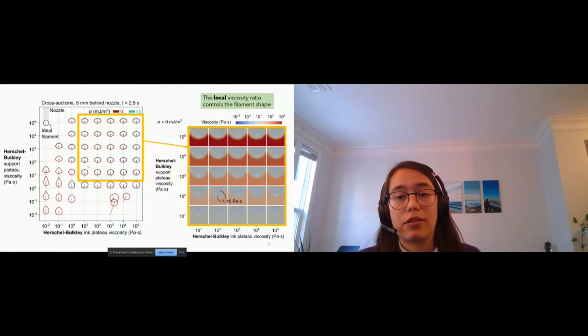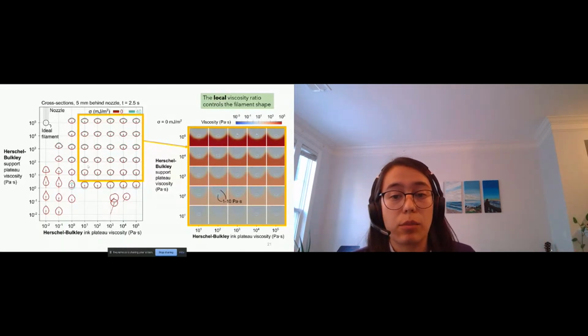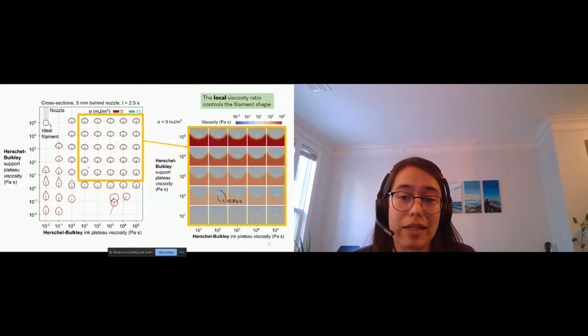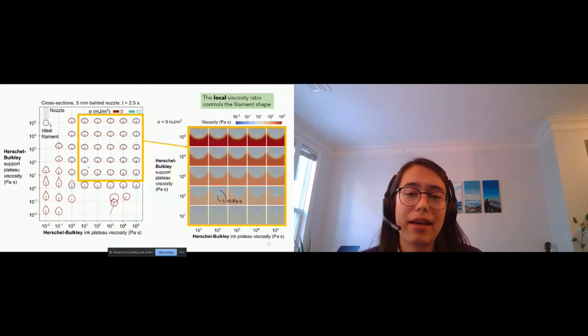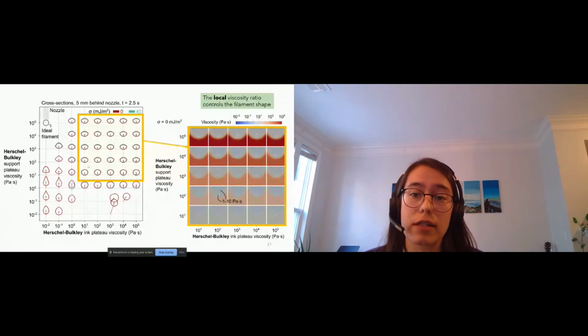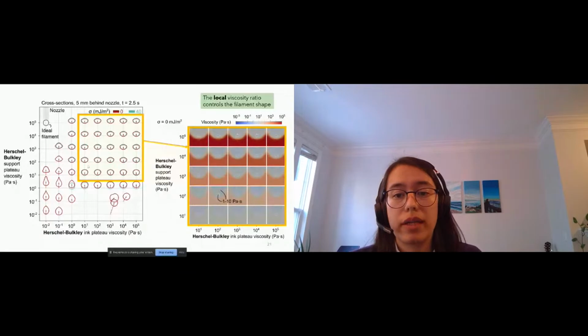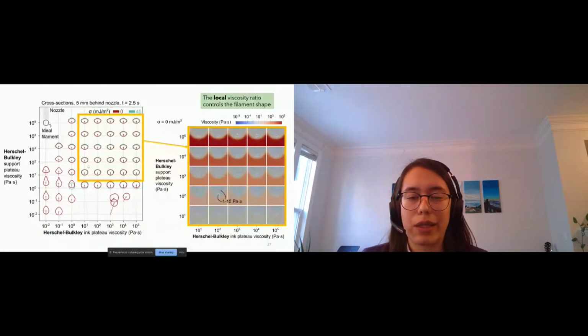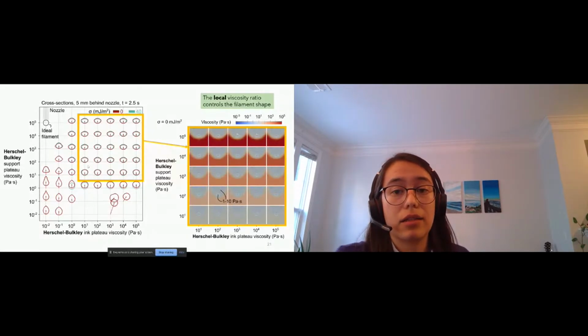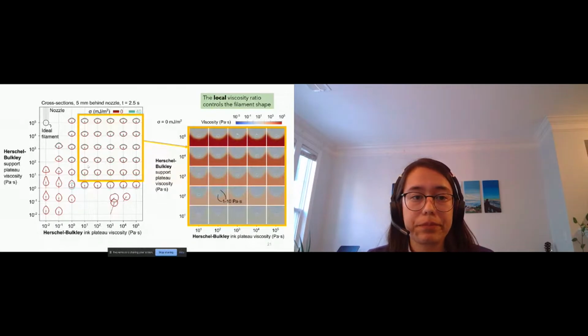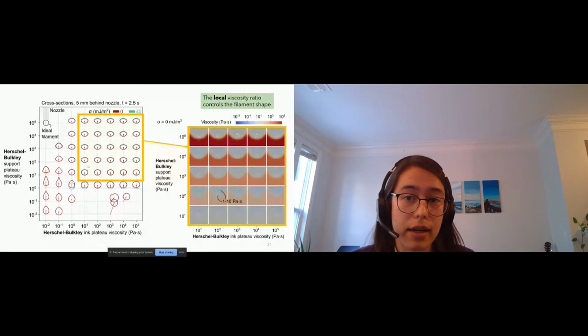And then there's a yielded zone outside of the filament where the support is at about 1 to 10 Pascal seconds. And then outside of that yielded zone, all of these supports are at a different viscosity, which is their plateau viscosity. So because we have the same viscosities within the yielded zone locally, that means we have the same local viscosity ratio for all of these plots, and that's why we get the same filament shape. So we learned here that the local viscosity ratio is what controls the filament shape.